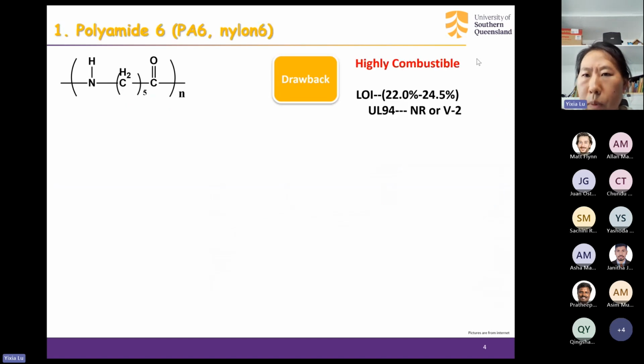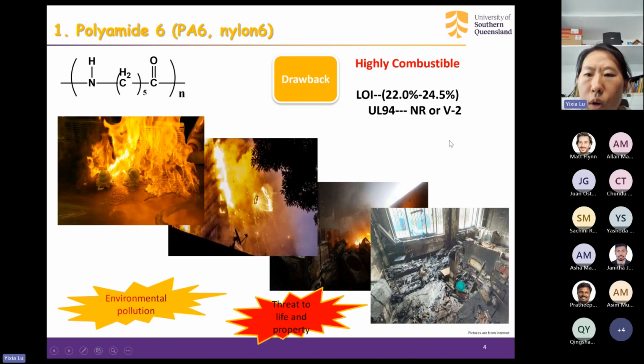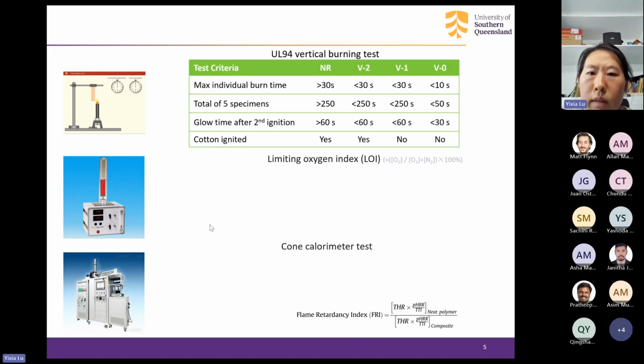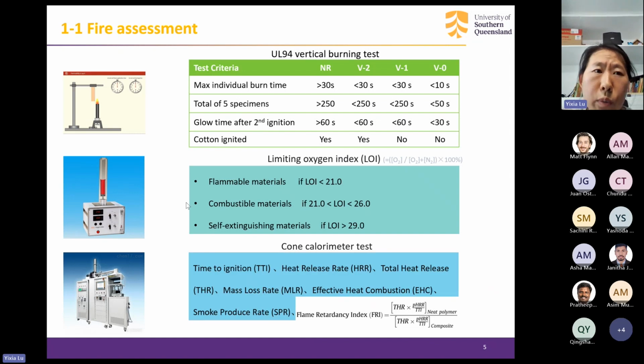It is highly combustible. As the test parameters say, the limiting oxygen index value is between 22% to 24%. This is a little bit low for materials, and it cannot pass the vertical burning test UL94, or it only has the V2 rating in the test. So the use of this material always gives rise to environmental pollution and threat to life and property, because sometimes heavy fire will happen.